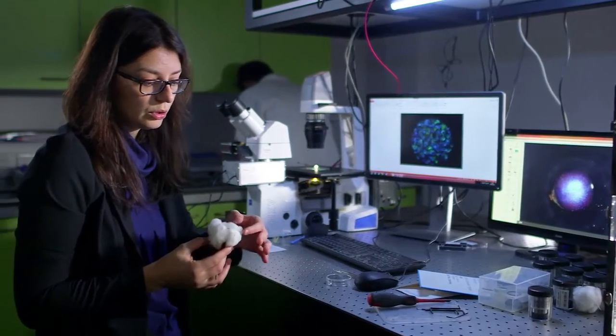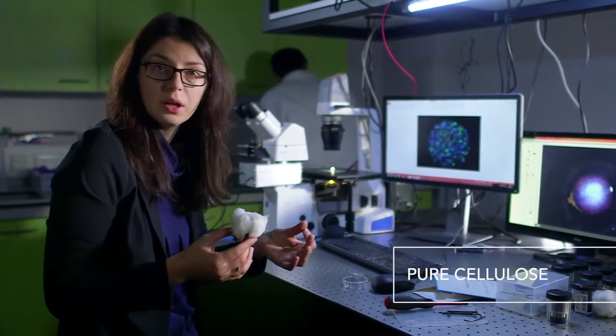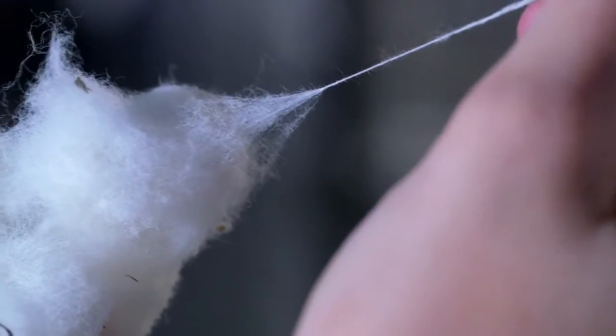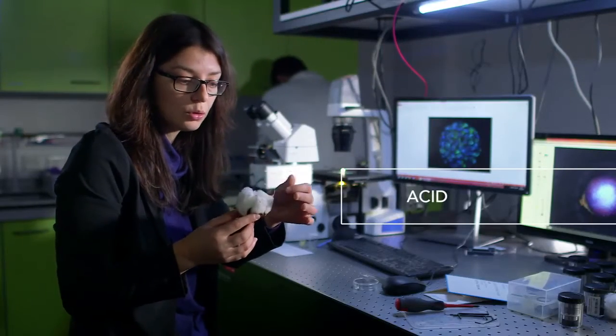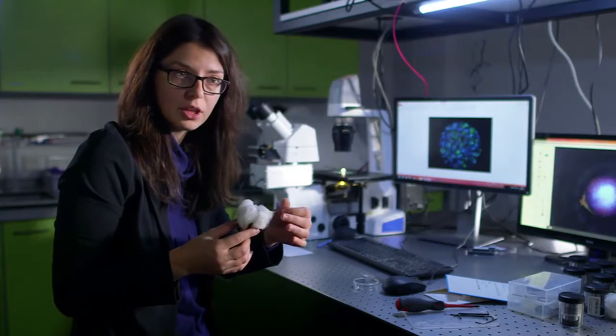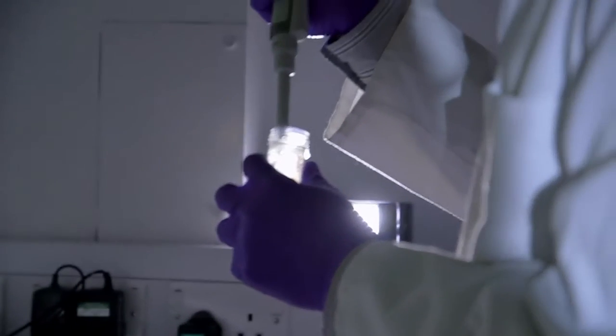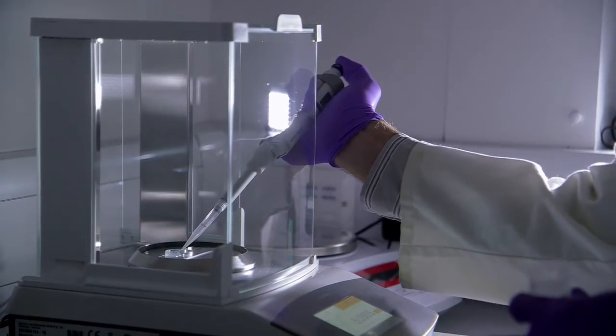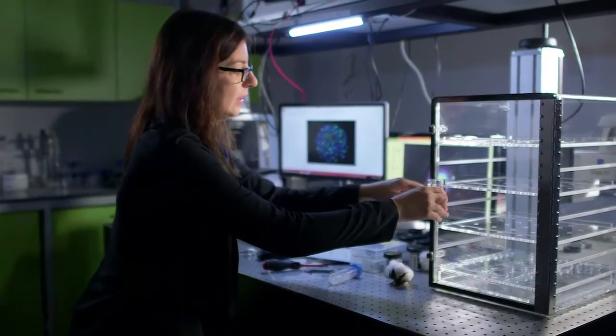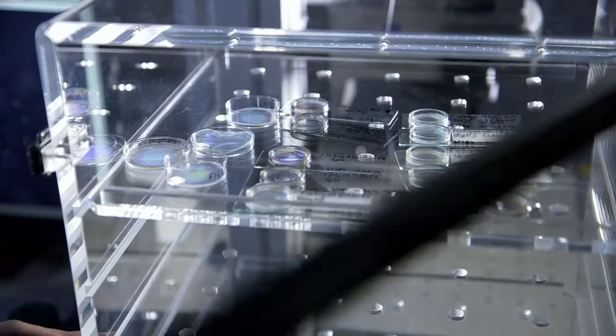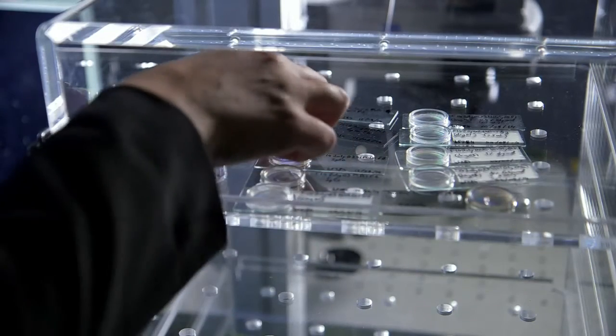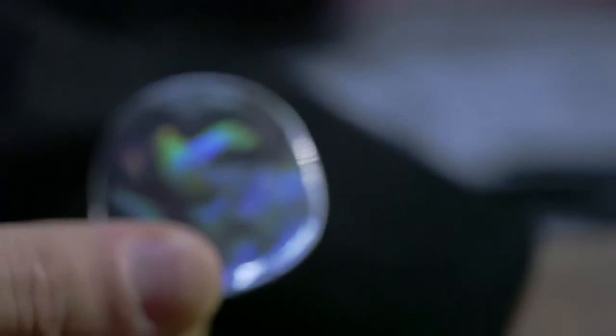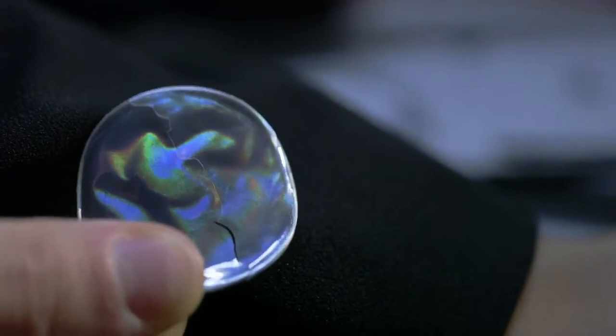So essentially what you do, you start from pure cellulose, that is the same one that you find from the cotton fiber. You have to use acid in order to cut out part of this fiber, natural fiber. Acid dissolves the material. We let them evaporate in a controlled environment. We wait and then you can obtain nicely colored film. And the color of this freestanding film is the same blue of the Pollia fruit because it has the same cellulose structure.